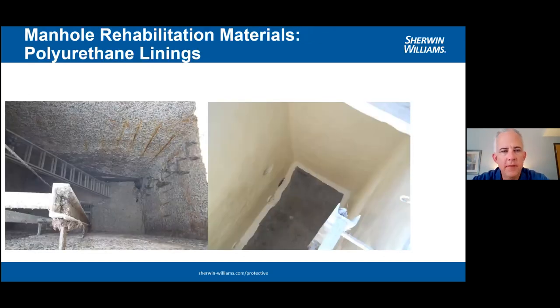The photo on the left is a photo of a lift station that we rehabilitated as well. And this is a picture using the polyurethane liners. From the photos, the epoxy liners really look about the same, and the end result ends up being about the same. But this specific one, on a military base up in North Carolina, we used the polyurethane because, again, there was some concerns with where this one was at. On that military base, they actually test explosives, and there was a lot of ground vibration, so they wanted to go with a polyurethane, something a little bit more flexible.